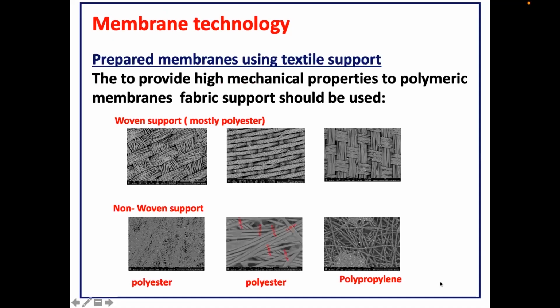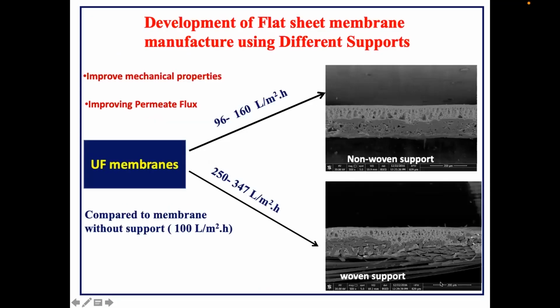For membrane technology, we prepared membranes using textile support to provide high mechanical properties to the polymeric membrane. The fabric support should be polyester and polypropylene, especially woven and non-woven. And this is the scanning electron microscope image for the different prepared membranes. We compared the woven, the non-woven, and without support completely, and we found that the woven gives us more productivity than the non-woven, and both of them more than without support.